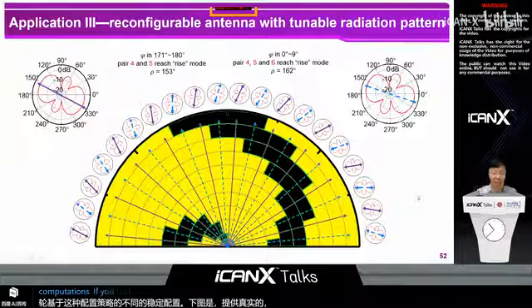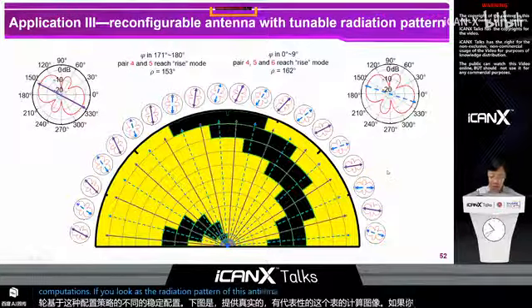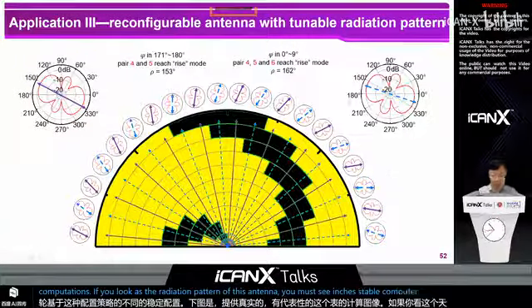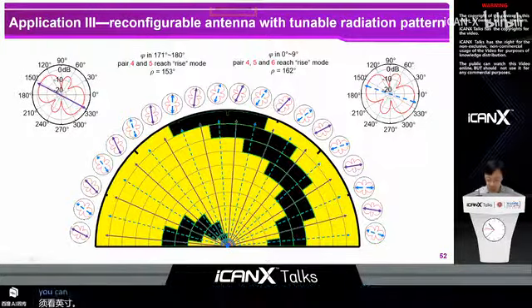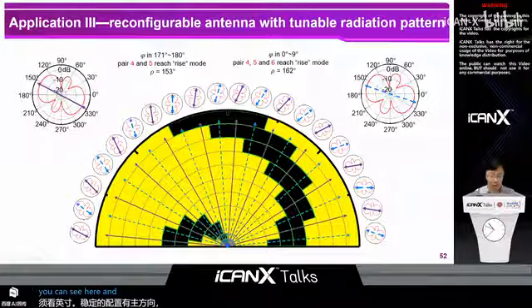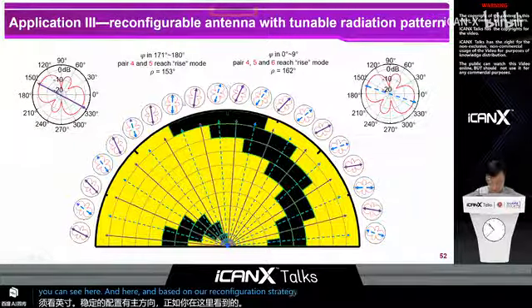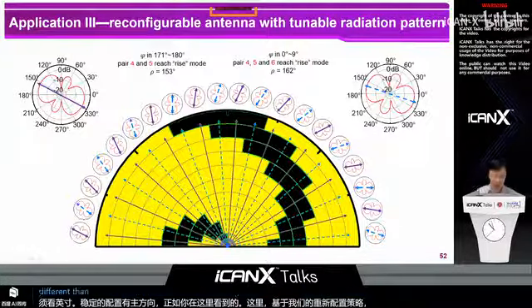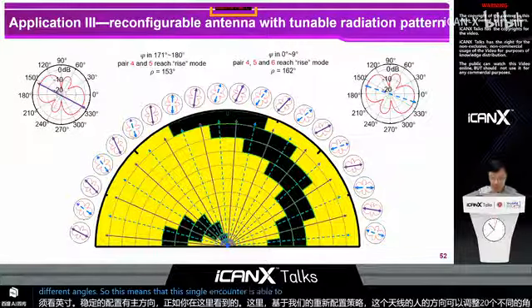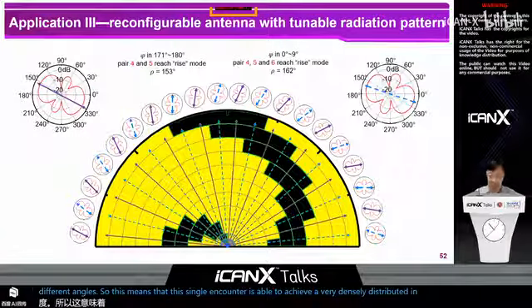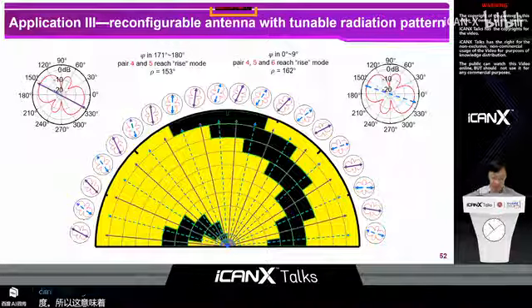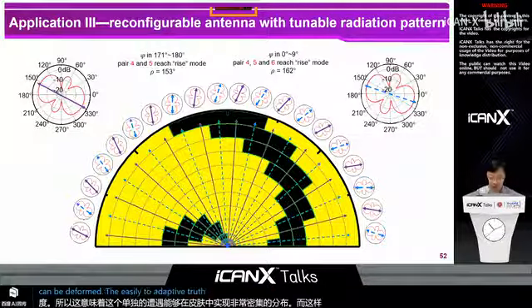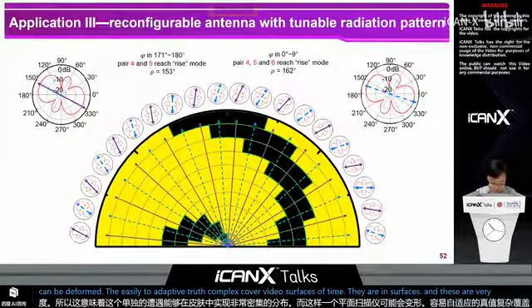If you look at the radiation pattern of this antenna, you will see each stable configuration has a main direction, as you can see here and here. And based on our reconfiguration strategy, the main direction of this antenna can be adjusted among 20 different angles. So this means that this single antenna is able to achieve a very densely distributed beam scanning. And such a flexible antenna can be deformed easily to adapt to the complex curvilinear surfaces or time-varying surfaces. And these are very challenging to achieve previously.